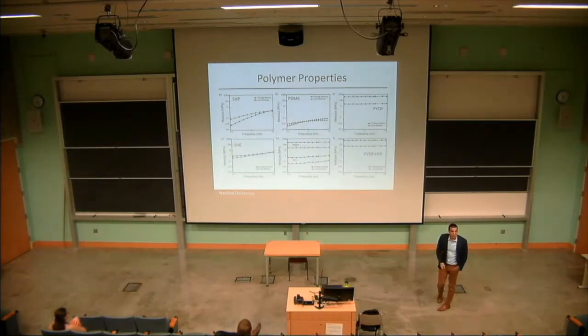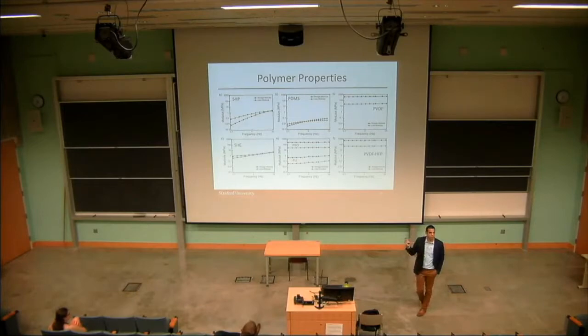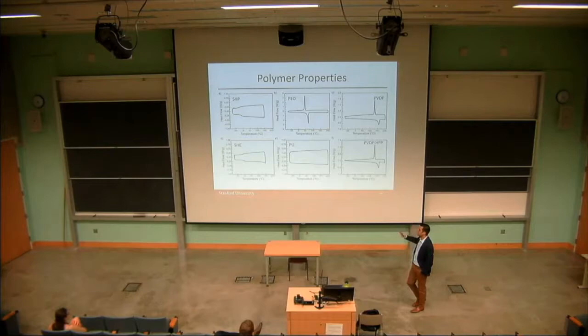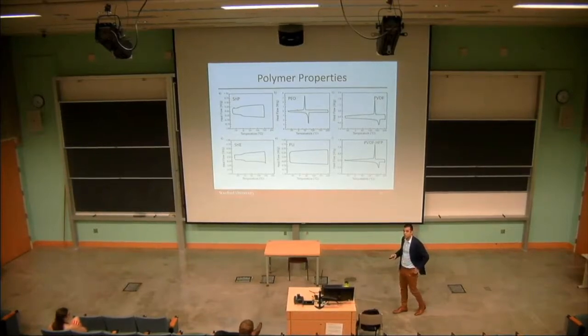We can look at the viscoelastic properties. So this is rheology and DMA. Again, the frequency response. So we have materials that are linear. In these ranges, we have these viscoelastic materials. Again, harder viscoelastic materials, softer ones, elastomers, just a wide range. But again, there's no clear correlation between these properties and the lithium morphology that we're seeing. And then finally, this is DSC. We have low glass transition temperature materials, highly crystalline materials, totally amorphous materials, but again, no real correlation. So we're looking at all of these polymer properties, but not really finding any sort of correlation between these properties and the lithium morphology.